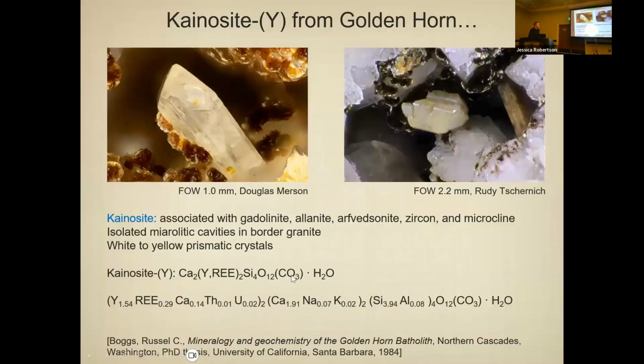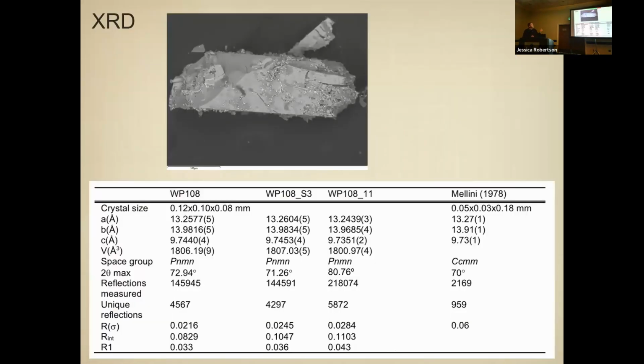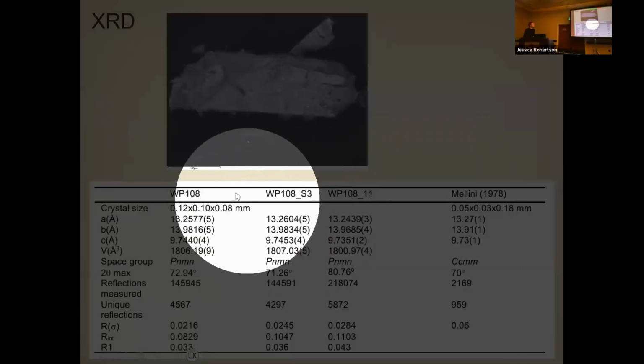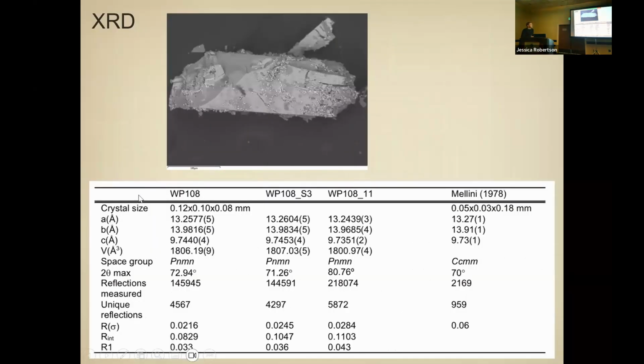So this is a calcium yttrium silicate with carbonate and water. Beautiful crystals. Of course, Rudy Tschernich's photos. So then we do X-ray diffraction. I thought this will settle it now for good. And so we take different samples from Washington Pass, and we look at the lattice structure, and we get